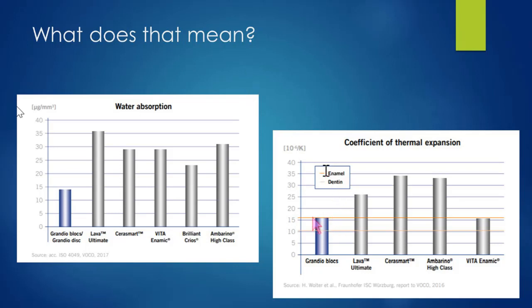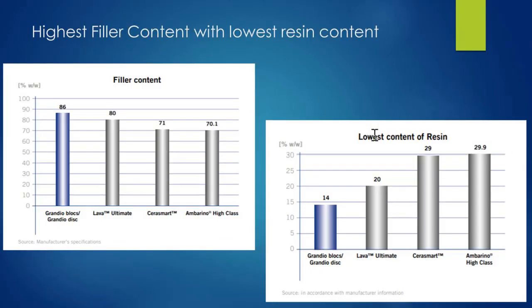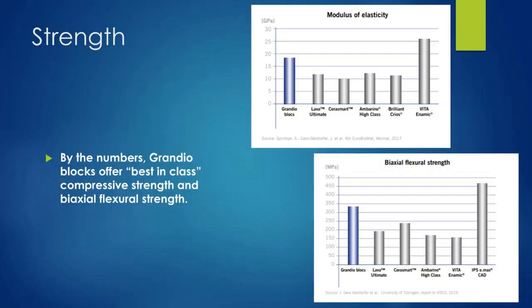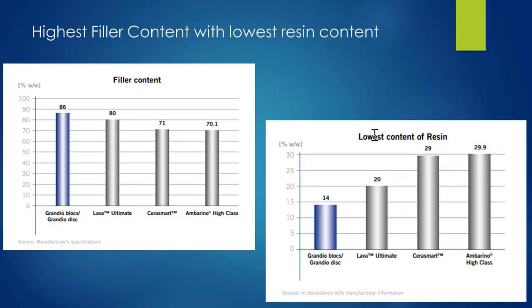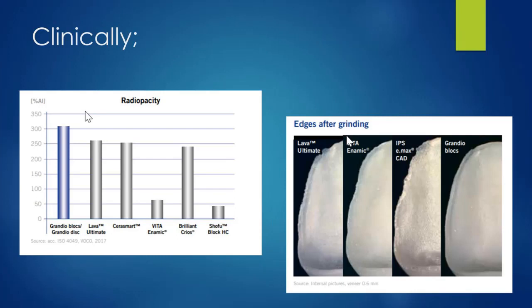So if you look at this diagram, the gold line across the top here represents the coefficient of thermal expansion of enamel. The gray line is dentin, and you can see that the only other material that even approaches Grandio blocks is the VITA Enamic. And if you remember from the previous slide, what we liked about this is that having the resin matrix with the ceramic filler actually gives us a really good biaxial flexural strength that even exceeds that of the VITA Enamic. So that's the reason this has become my go-to product.